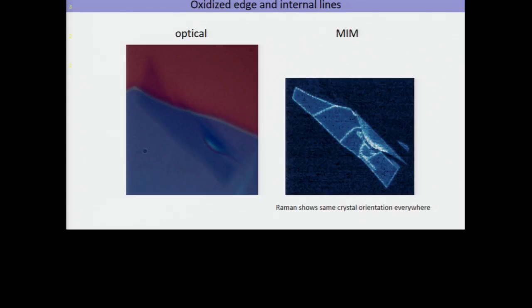Yeah, if you could measure the conductance of that, you'd expect it to be 2e squared over h, and this would be 1, right? But since these are kind of quasi-ballistic, extended one-dimensional objects, it's not entirely clear, at least to me, what you're really measuring when you do the MIM signal and how you should model that. So if people have thoughts about this, my thought is just, without knowing how to model it, just the ratio of the MIM signal there to the edge. The MIM signal is not proportional to the conductance, unfortunately. It's very nonlinear in the conductance, and it's somewhat non-local.